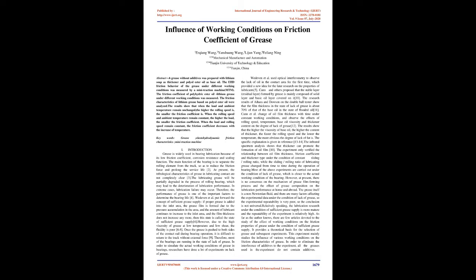The EHD friction behavior of the grease under different working conditions was measured by a mini-traction machine, MTM. The friction coefficient of polyhydric ester oil lithium grease under different working conditions was measured. The friction characteristics of lithium grease based on polyol ester oil were analyzed.